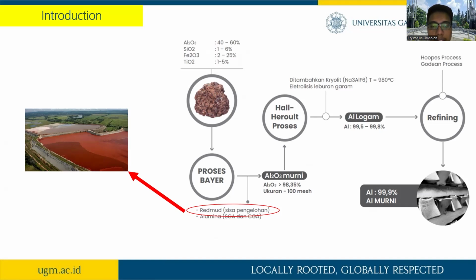In 2021, the industry will produce 4.3 million tons of chemical-grade alumina per year and 1.2 million tons of smelter-grade alumina per year, resulting in approximately 4.4 million tons of red mud waste per year. Red mud contains alkaline compounds with high pH, is very fine, and sometimes contains harmful minor elements that cause serious problems for the environment. Therefore, research for the handling and utilization of red mud is very intensive.